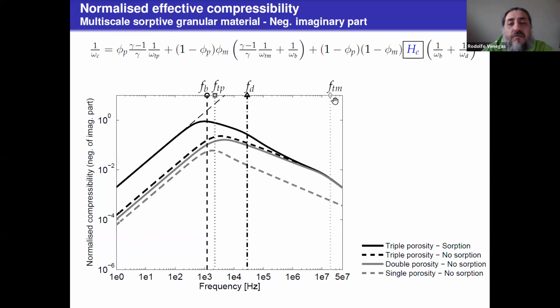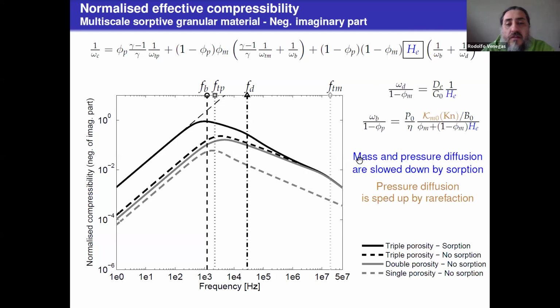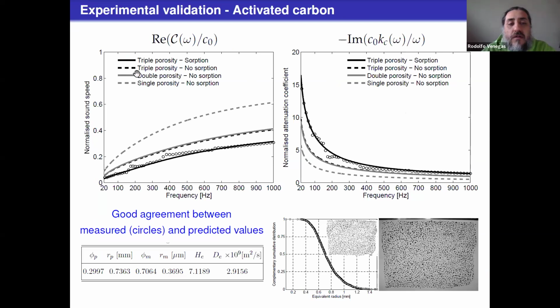What happens is that because of sorption, in particular, the transport processes are slowed down, meaning that the characteristic frequencies go down in values. And also because of this sorption, the magnitude of the imaginary part is much larger than in the case of triple, double porosity, single porosity with sorption. Those are the two effects that can happen, and these are very convenient effects because they can lead to a very slow normalized speed of sound, as shown here, and a very large attenuation coefficient at low frequencies, as shown here.